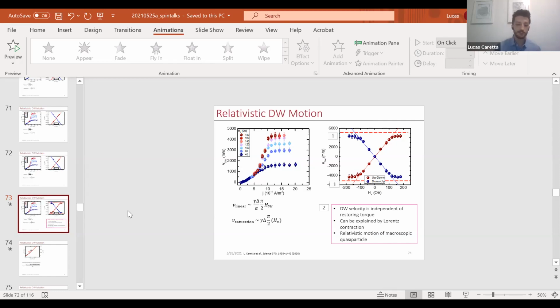So the short answer to your question is, in this material system, this is as fast as you can move a domain wall. In principle, you can go faster in other material systems, and you can see effects like Cherenkov-like radiation, at least it's predicted. When we drive the domain wall at this velocity, we see some odd things that we can't explain yet that might look like Cherenkov radiation, but we're not sure yet, which is why I haven't really talked about it here. So definitely you're on the right track with the interesting things you can do here.